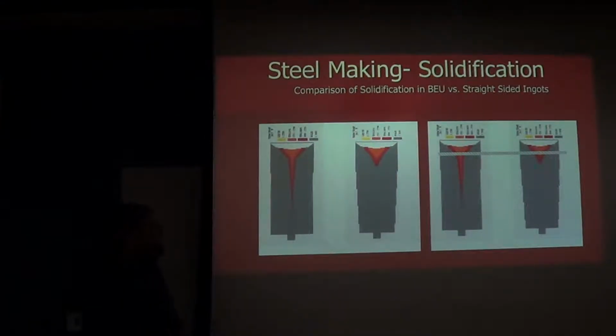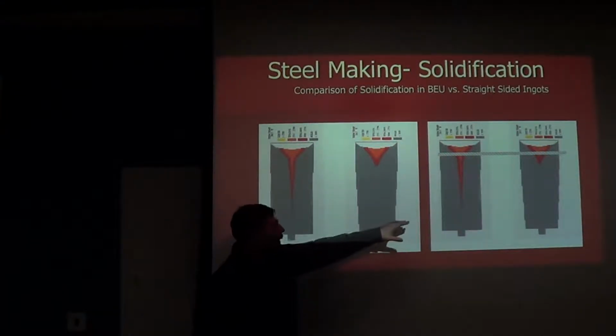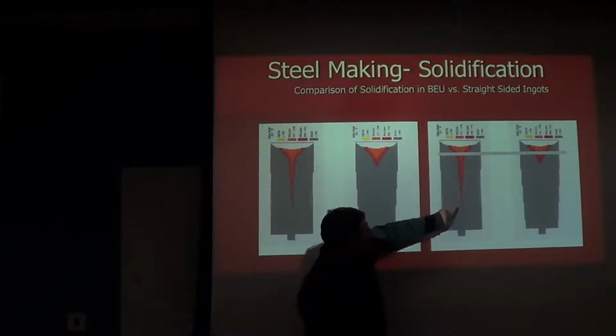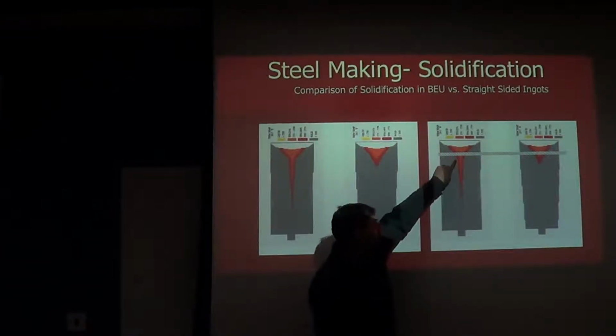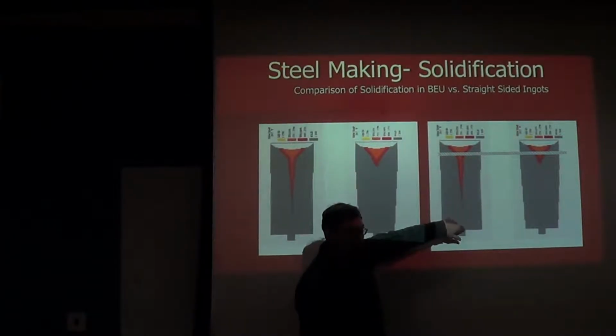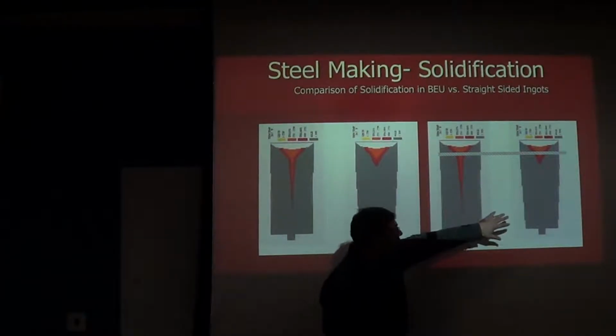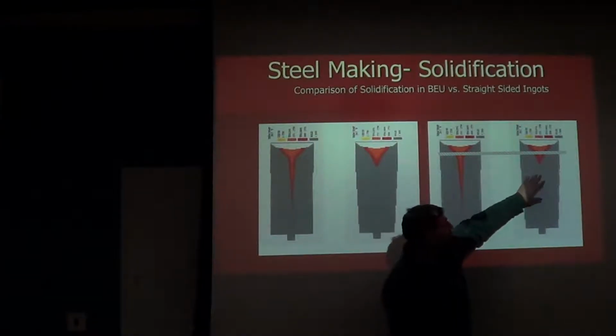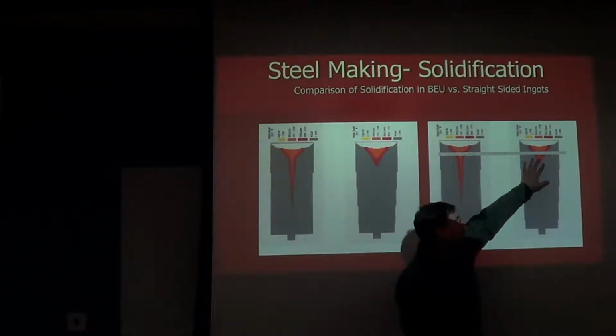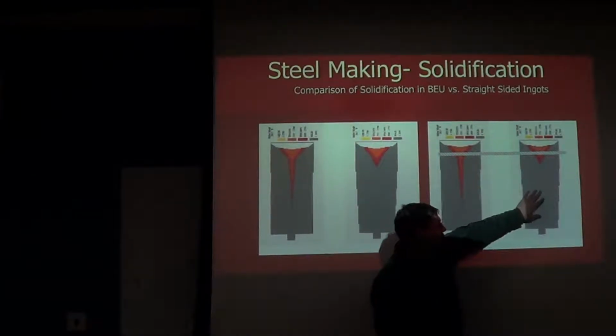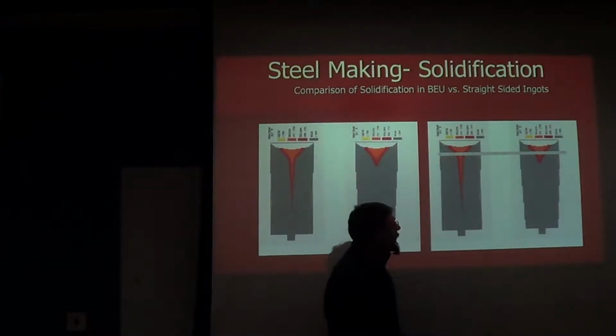And when we get near the end, we can see that the straight-sided ingot is solidifying here and here basically at the same time. That means that you're going to have some amount of piping or holes all the way down almost to the very bottom of the ingot, where in a tapered ingot, that condition will be limited and will be much closer to the top, and then you'll have much fewer of those holes throughout the body of the ingot.